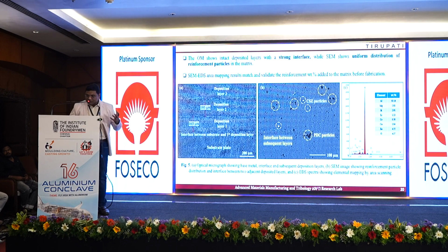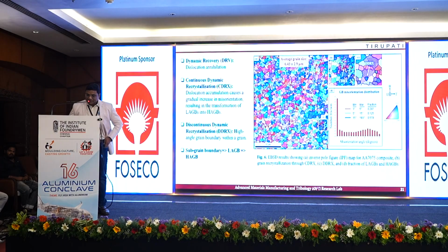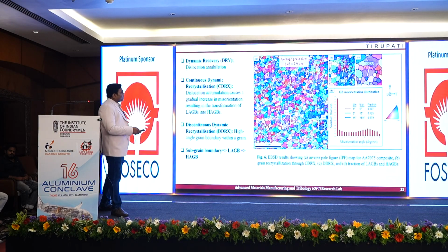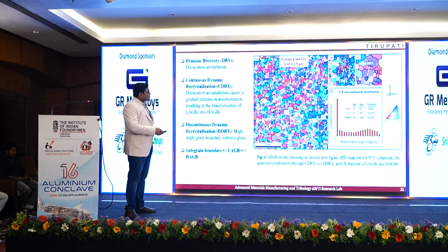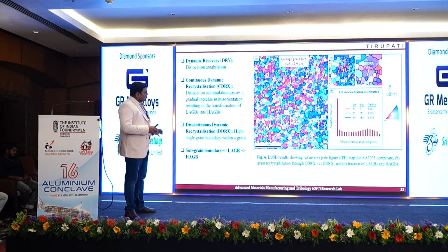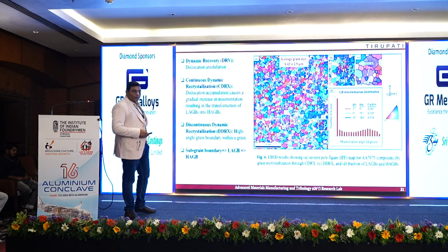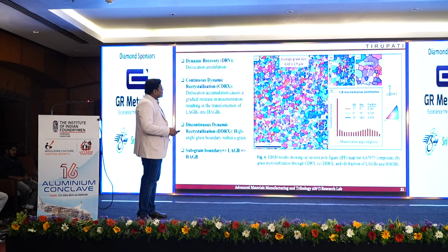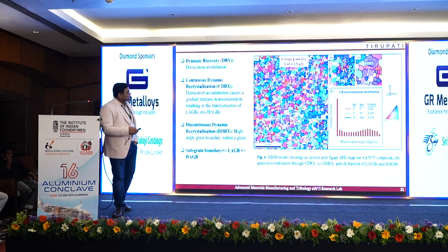The beauty of this process is the microstructure and refinement of the particles. You can also see this is the microstructure we studied using electron backscatter diffraction techniques. You can see here the microstructure, and the average grain size is around 6 micron.